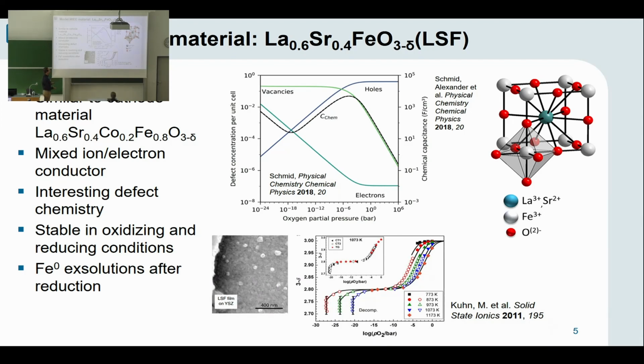And when we reduce the material, the electron hole concentration decreases and the charge compensation of the acceptor doping switches to primarily oxygen vacancy compensation. So the material becomes a better oxygen anion conductor in reducing conditions, and the electronic conduction mechanism switches from P-type to N-type. So we can tune the electrochemical properties of the bulk a lot by the oxygen partial pressure.